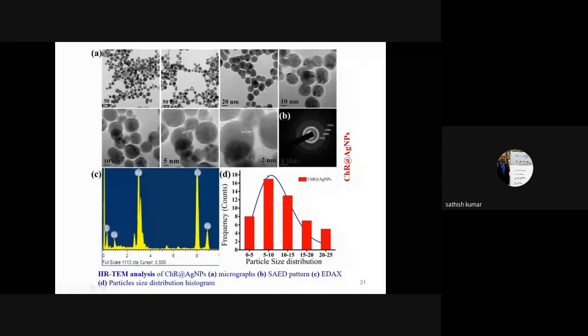Here we found that the synthesized silver nanoparticles are largely monodispersed in nature. And here you can see the high resolution image clearly shows the lattice fringes, which corresponds to the face-centered cubic crystalline nature of the particle. And also the selected area electron diffraction pattern also shows the presence of face-centered cubic crystalline nanoparticles. This is supportive data for the XRD analysis. So the particle size distribution shows that particles are in a narrow range with a size range of around 5 to 25 nanometer, with an average size of around 14 plus or minus 6 nanometer.